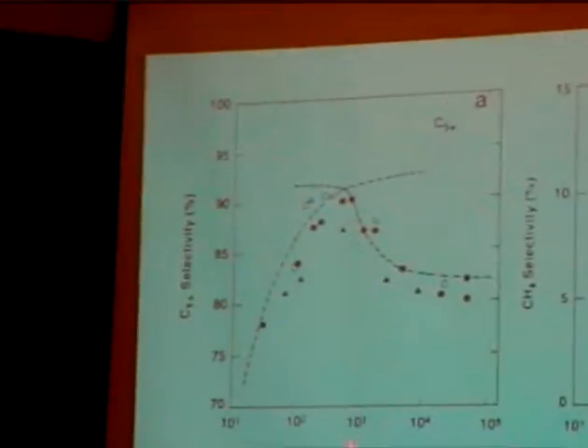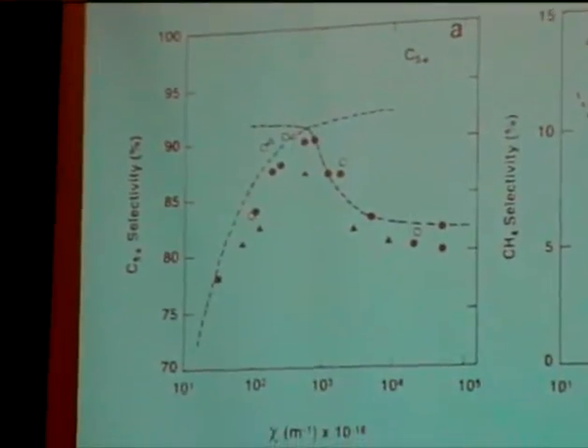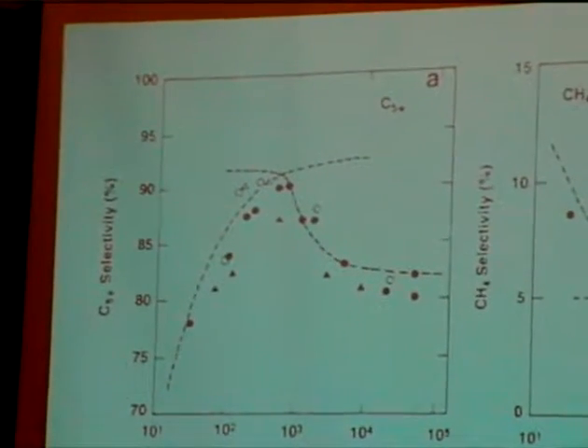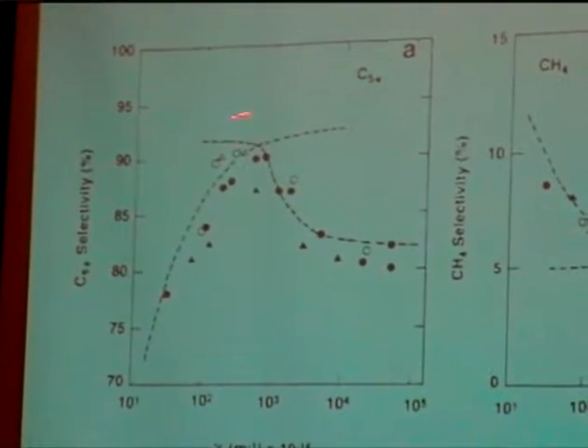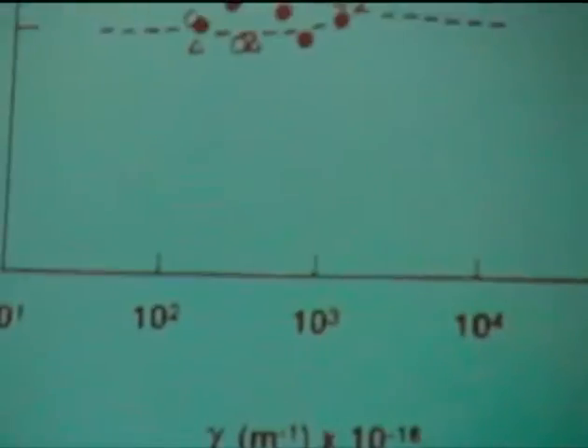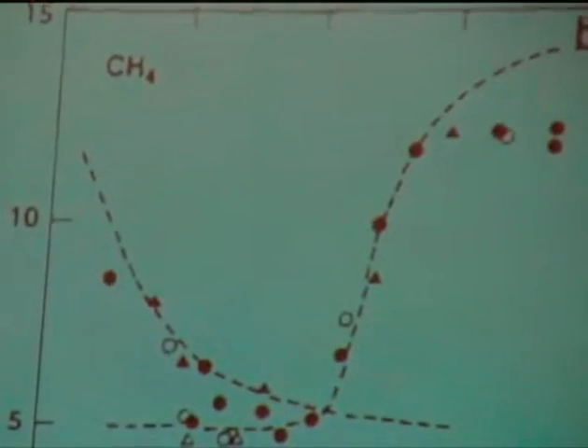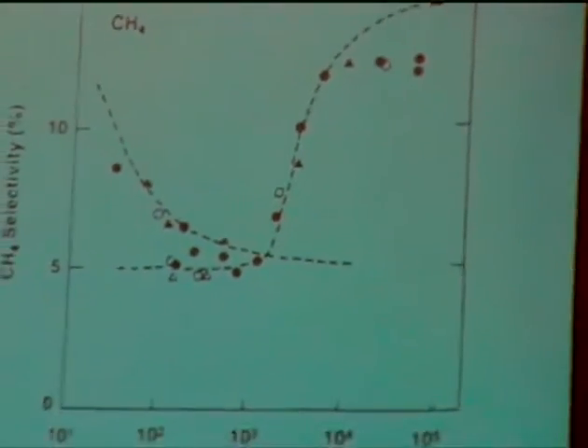In the next figure we see an increase in C5+ selectivity with increasing value of chi through a maximum, with a magical value here of about 200 times 10 to the 16 reciprocal meters. Then it decreases, because you get into diffusion-limited arrival of CO at the sites, and the result is the rate starts to go down.